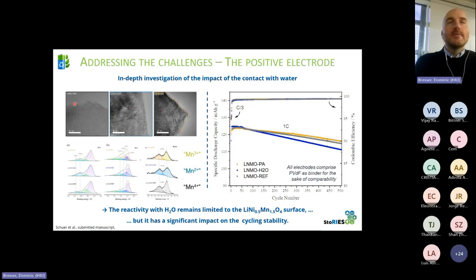I should add that this lithium nickel manganese oxide operates at 4.7 volts more or less. So we charge the cell to about 5 volts, 4.9, meaning that we have potentially a lot of electrolyte oxidation. And this metal phosphate layer plays a similar role, let's say, as the SEI on graphite. So it's kind of kinetically stabilizing the electrolyte at the interface. And that's why the slightly superior performance compared to the reference material that was not in contact with any water.